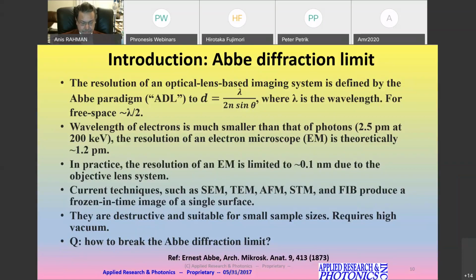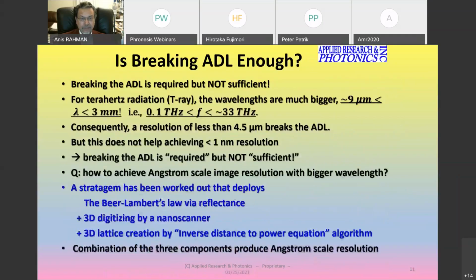So we came up with a different technique using bigger wavelength and still doing the lattice-scale imaging. And as you see in the blue, the stratagem has been worked out that deploys the Beer-Lambert's law via reflectance. So we rewrite or modify the Beer-Lambert's law in the reflectance domain, and then we use a 3D nanoscanner for digitizing an object, and then we use a special algorithm to generate the image.